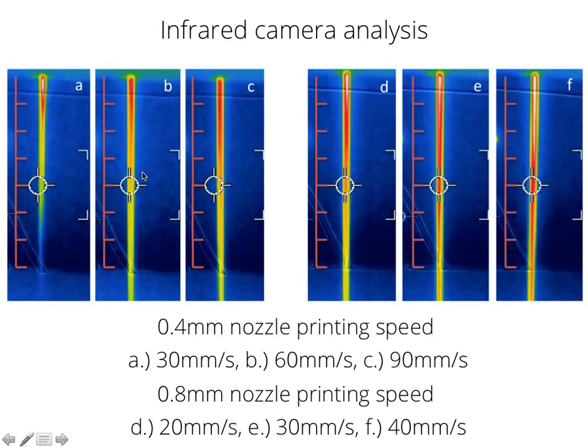We can see here the 0.4 millimeter nozzle printing at 30, 60 and 90 millimeters per second, and here the 0.8 millimeter nozzle printing at 20, 30 and 40. The surface area temperature hypothesis kind of fits for A here for 30 millimeters per second. You can see here a short section only maintaining the heat for a short time, and as such a small area that might emit particles. And we can see already here that after a while the extruded filament already reached ambient air temperature. We can see here for 60 millimeters per second that it can maintain a heat longer, or a greater surface area or greater length of filament that can emit particles, but this also goes for the 90 millimeters per second.